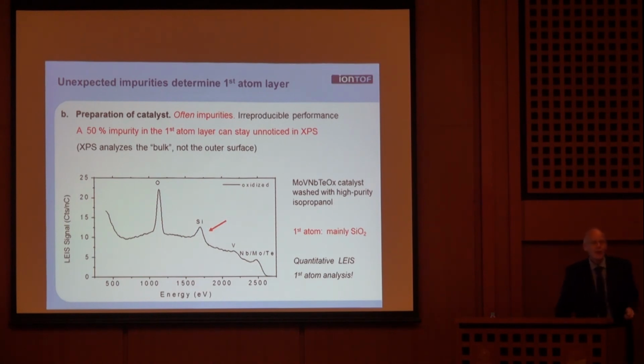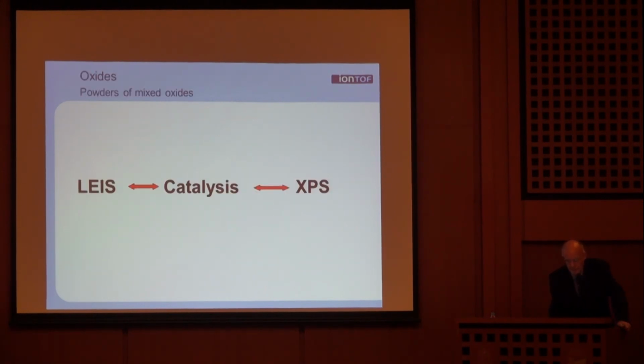So you have to learn. If you do any other technique, generally I compare to XPS, but of course other possibilities. That gives of course a lot of interesting other information, but it looks much deeper. And because of that, they did not see, or they thought it was not relevant, the silicon. Here we say more than 50% of the surface is covered by silica. Okay.